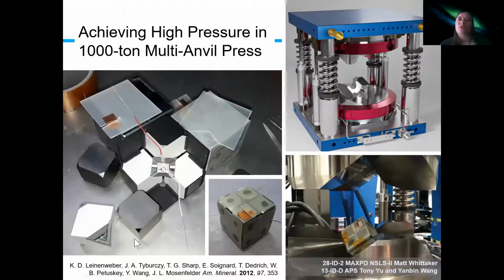And so quickly, what happens here is we have a ceramic octahedron that sits inside of truncated cubes, and we put little strips of boron nitride in our gasket material to act as an X-ray window. And then that goes inside of the press, and I've worked with the wonderful folks at NSLS2 and at the APS to do these syntheses.